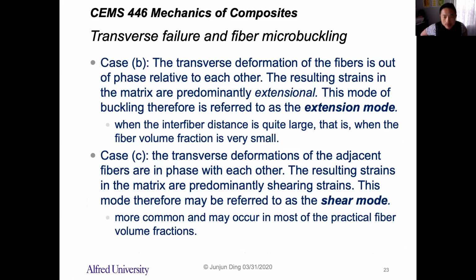And this is the case fibers buckle in a cooperative manner. So for the case B, the transverse deformation of the fiber is out of phase relative to each other, right? So it's out of phase relative to each other. The resulting strains in the matrix are predominantly extensional, and that's why this is referred as the extension mode. So this is the case when the interfiber distance is quite large. That means the volume fraction of the fiber is very small.